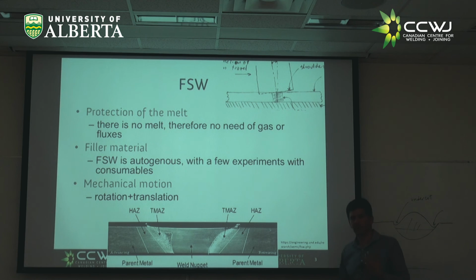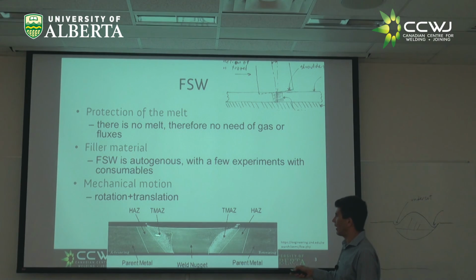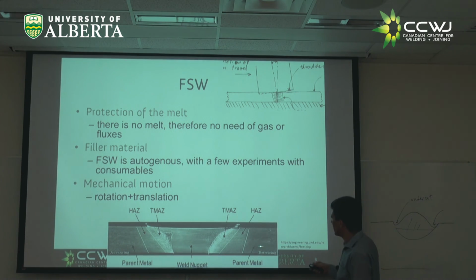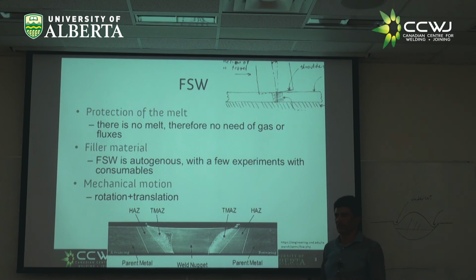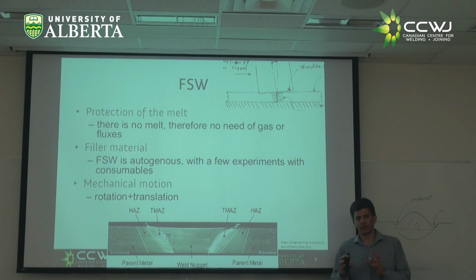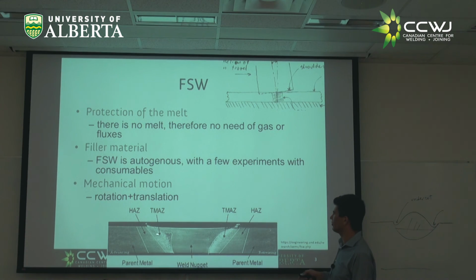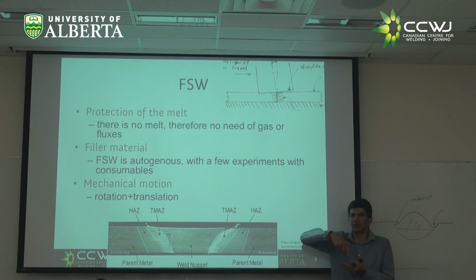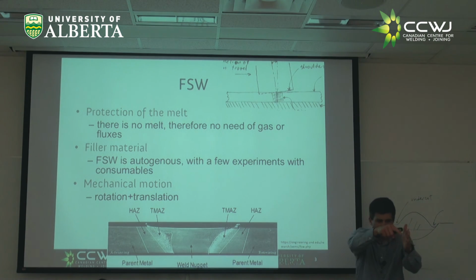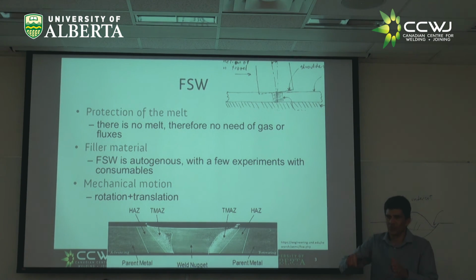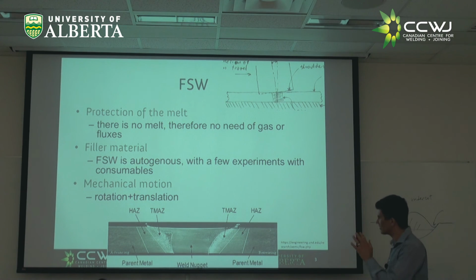And when you see a cross-section, it looks very different than a fusion weld, because you have the parent metal here, the base metal, and a heat-affected zone. In addition to the heat-affected zone, you have a thermomechanically affected zone. That's new, because when you melt things, you don't have thermomechanical actions, right? And they call the weld nugget here where it was moving. Why is this not symmetric? Well, when you're spinning and moving, one side is called the advancing side, it spins in the direction of motion, and the other spins back, right? So that gives you an asymmetry. That's not a problem.